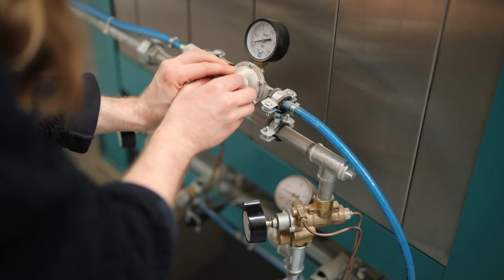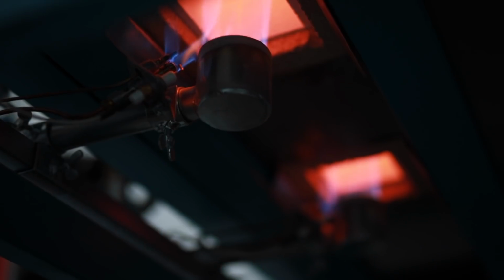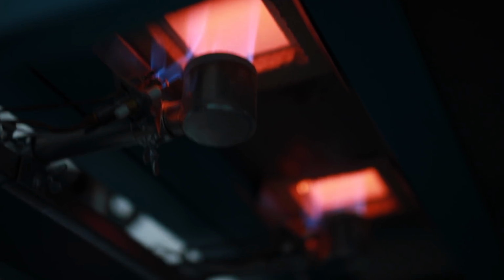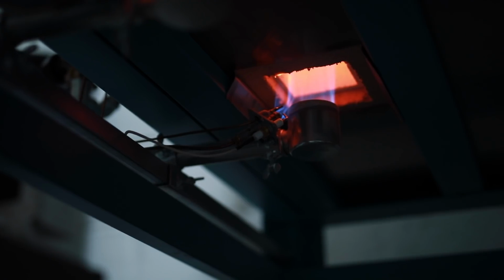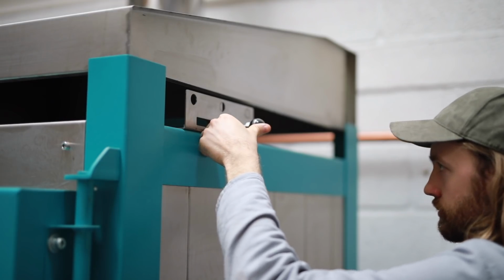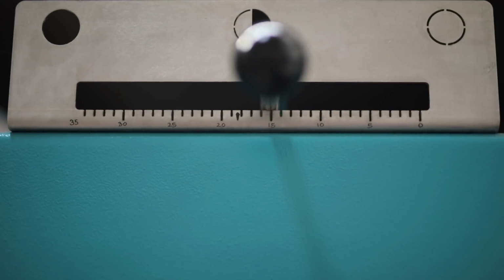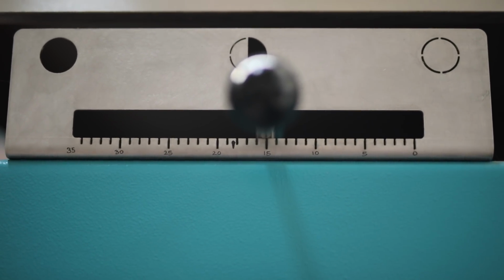The whole reason that I own a gas kiln is that it opens up the possibility of firing in a reduction atmosphere, which is something that's just not quite possible to do in a conventional electric pottery kiln. Once the kiln's temperature reaches 860 degrees Celsius, I initiate reduction. I do this by sliding the dampers over the flues of the kiln to be half closed. I also drastically increase the gas pressure and the air pressure. This causes the fuel that's burning inside the chamber to burn inefficiently, as there simply isn't enough oxygen inside. This is why flames start to emanate from the flues, as you can see here, and out of the spy holes in the door too.